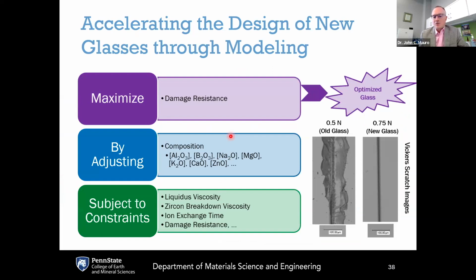This is an example of one of the Gorilla Glasses that has been developed, that dramatically improved the damage resistance of the glass. Here, what we wanted to do was maximize the property that we cared about the most, which was the damage resistance. We did that by adjusting the chemical composition of the glass. You'll note that silica is missing here, and that's because not all the components are independent of each other. Silica is just 100% minus the summation of everything else. And then it's subject to the constraints on all the other properties that we care about from both a product-facing point of view as well as a manufacturing point of view. And if the models are working well, this should spit out the formula for the optimized glass. And in fact, that's exactly what was done here.